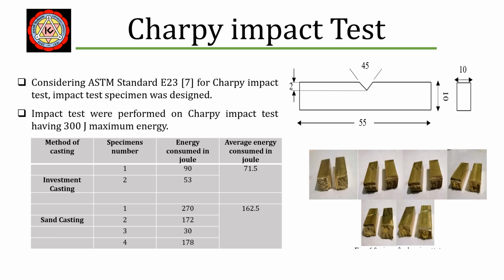Charpy impact testing was performed by considering the ASTM standard, in an impact test machine having maximum 300 joule energy at Kathmandu University laboratory. There were two specimens of investment casting and four from sand casting. This shows the total average energy consumed in joules. The average energy consumed in sand casting is higher than the average energy consumed in investment casting. So, there were casting defects in the investment casting of the 14 kilowatt Francis runner, might be the conclusion from this test. These are the specimens after the impact test.